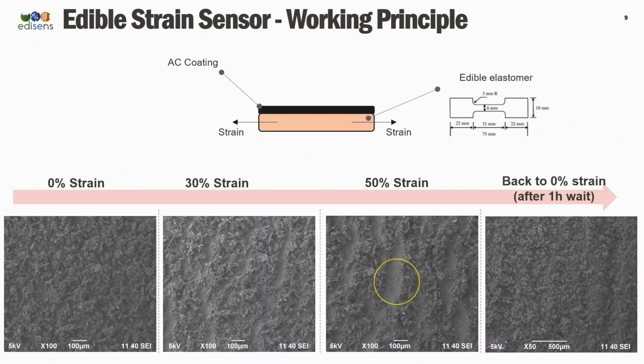Another application we have tried is strain sensing. So we have applied the coating onto an edible elastomer, also made with gelatin. Basically, we have a material that you can stretch. And you will see from the SEM analysis that as you strain the sample, microcracks appear in the coating, which of course reduces the conductivity. And these cracks are also self-healed, meaning that you can reuse the sample for strain sensing.